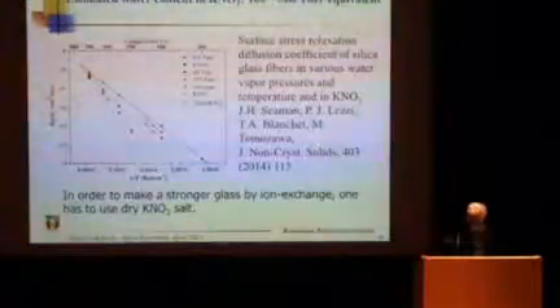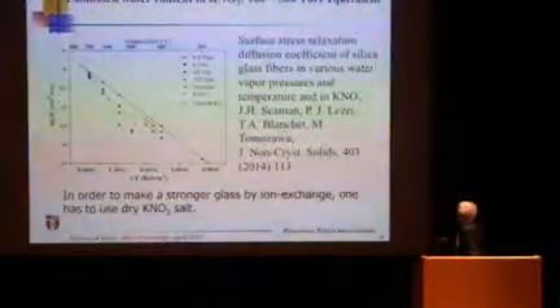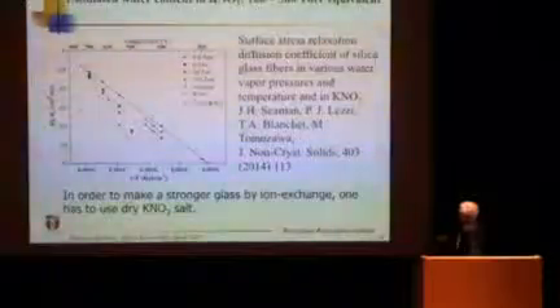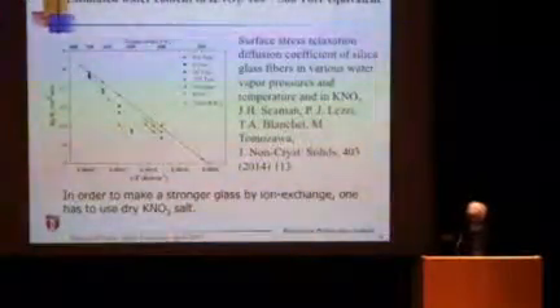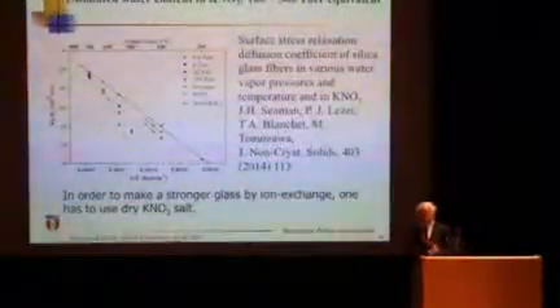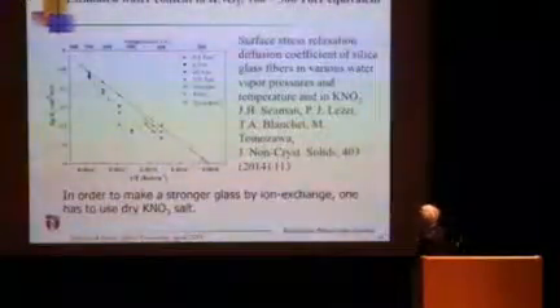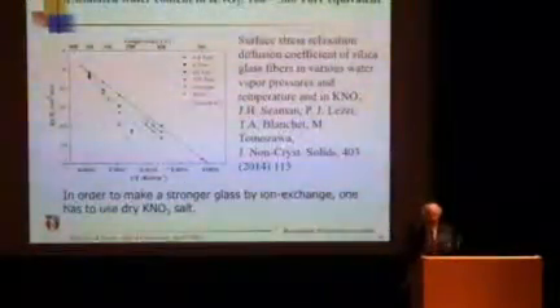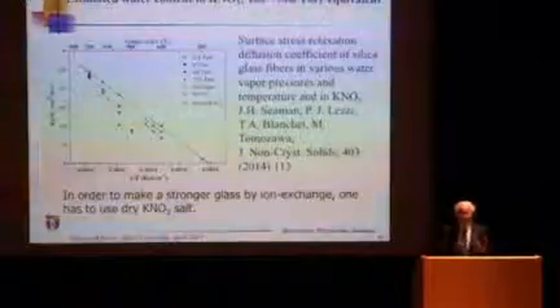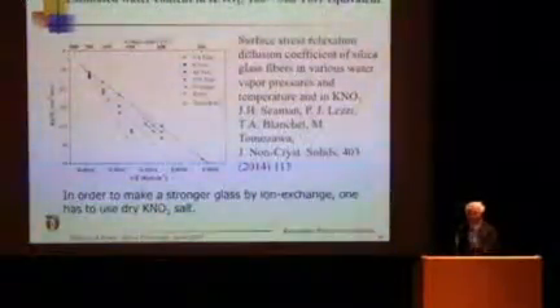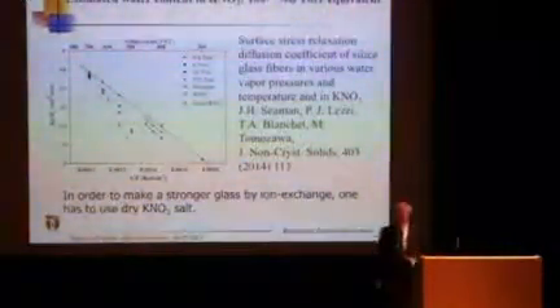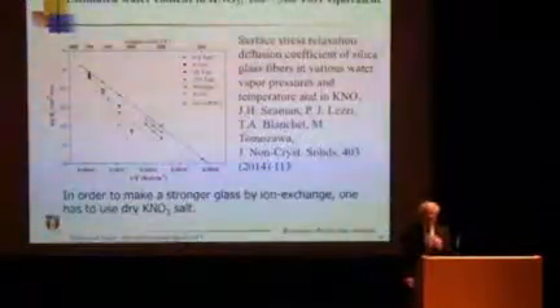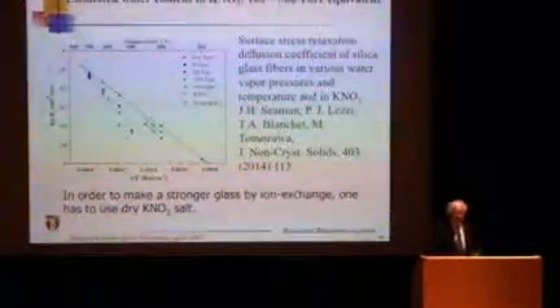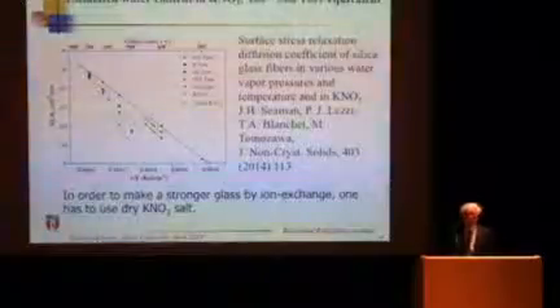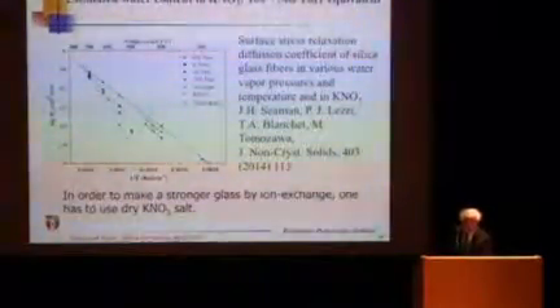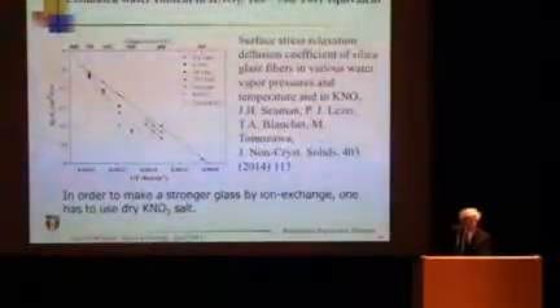This was the original silica glass in air, and this was in molten salt. From this, we can estimate the water vapor in the molten salt is 200 to 300 torr equivalent. Of course, it's not in a vapor form, but there is a small trace amount of water. So if you'd like to make a better ion exchange glass, one way is to dry the potassium nitrate, make it as water-free as possible. Then you can make even better, higher strength glass.